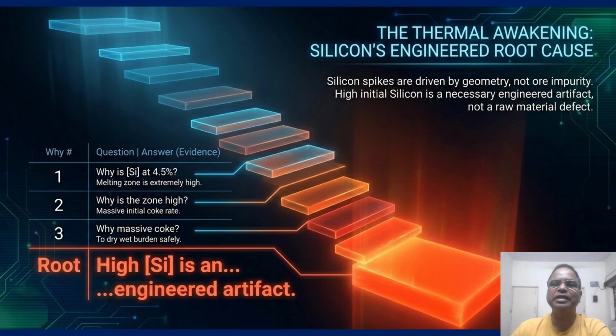High silicon is not a raw material failure, it is basically an engineered result of a heavy initial coke rate used to dry the burden safely. So try to understand the consequences of higher silicon. If our understanding is very clear, we can control the situation within a short stipulated time, which will be better, as we have discussed already, for everything like logistics and so on.